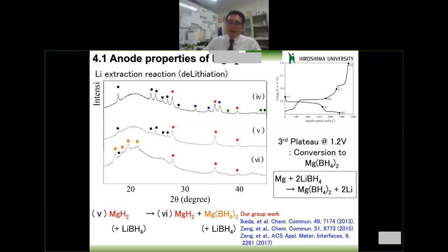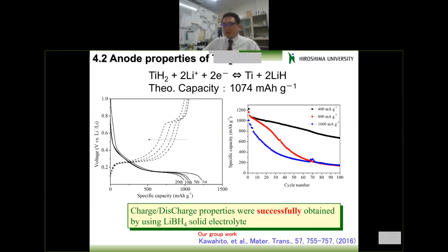But anyway, we somehow characterized this material. And then finally, we limited the charge-discharge voltage, and some good cycle properties were observed. Those results were reported in these papers. And then the next topic is titanium hydride. And titanium hydride is quite a simple reaction.